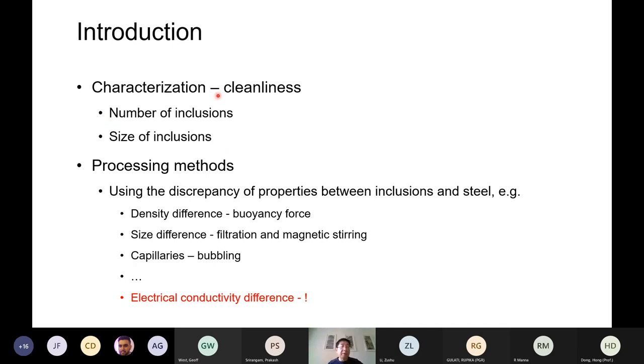For a lot of different steels, such as bearing steel, you need to get rid of the inclusions. So the inclusions should be removed. So that is a case for our research. In the processing method, how do we remove those inclusions if you do not want them in your steel? If you want to remove them, first you need to identify the difference between inclusion and liquid steel. So according to their property difference, we remove those inclusions.